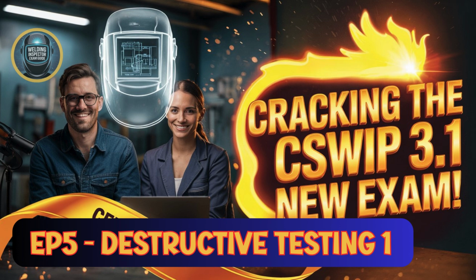Okay. Now, you mentioned looking at the broken pieces afterward gives you more info. Yes, there's valuable additional information you can get visually. One key thing is the appearance of the fracture surface, specifically the percent crystallinity. Crystallinity. Yeah, a brittle fracture surface looks bright, granular, crystalline. A ductile fracture looks duller, more fibrous. So by estimating the percentage of the fracture face that looks crystalline, you get a measure of how brittle the failure was. 100% crystalline means a completely brittle snap.